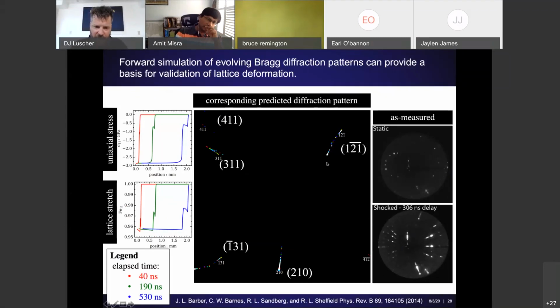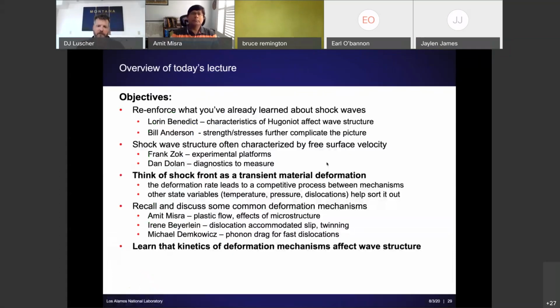but it's meant to illustrate the point that the diffraction pattern is related to the deformation of the lattice, and the lattice deformation is a result of the imposed deformation and whatever competing mechanisms were operative to accommodate inelastic deformation. So the net, what's left over, is the elastic lattice deformation. So this is some way to constrain or close those models.